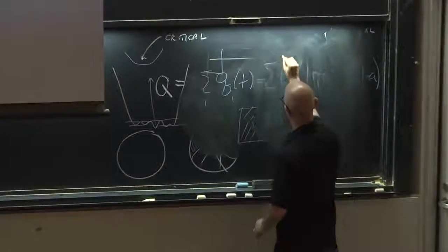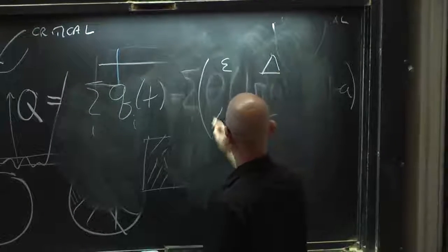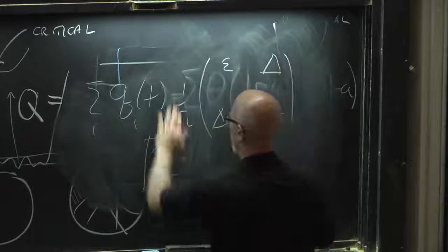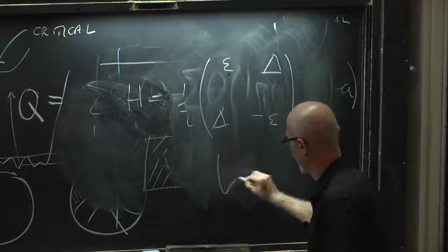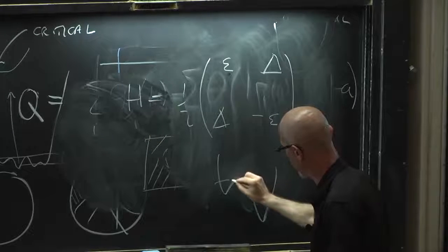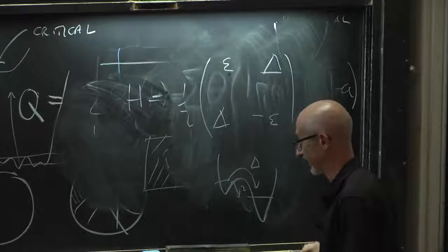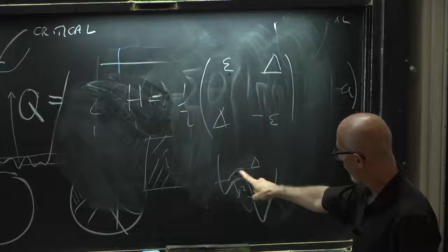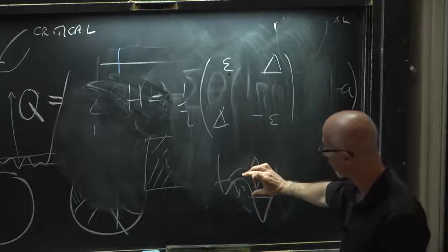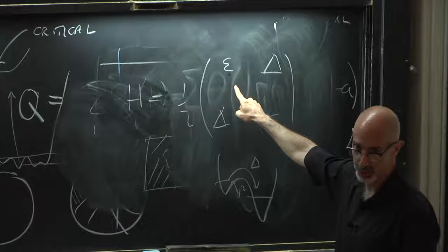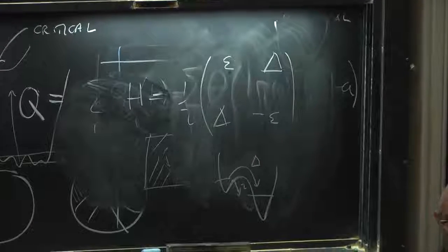your Hamiltonian for your two-level system is a tunneling matrix element. Right? There's a bias energy, which is basically epsilon, and then a tunneling matrix element, delta, that can connect these two states. There won't be many two-level systems that are active at 1 Kelvin because you need the tunnel splitting, which is the square root of epsilon squared plus delta squared, to be on the order of 1K. Otherwise, the two-level system is frozen.